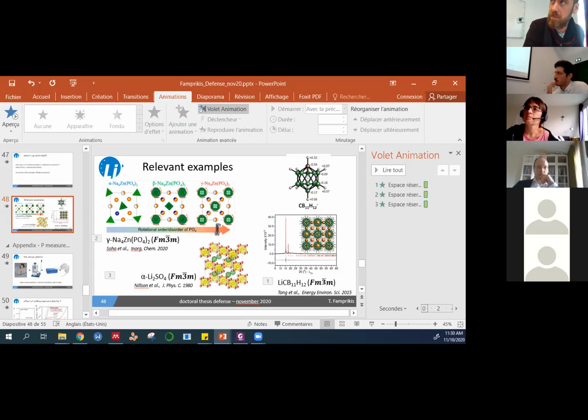By calculation, no. We can get an idea of the change in entropy upon phase transition by using the latent heat that we see, and by assuming that the latent heat is equal to the change in entropy over the temperature of transition. I've done this calculation in the last chapter, but not by DFT calculation. But indeed, you would expect a sizable entropy difference between the classical solid beta phases, alpha and beta, and then the gamma phase, for sure. This is another key hallmark of plastic crystal phases. Yes. Anyway, okay. Go ahead.